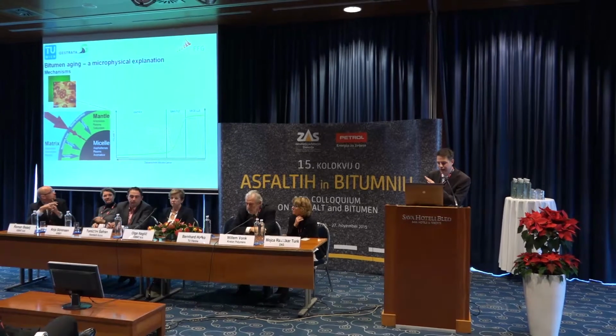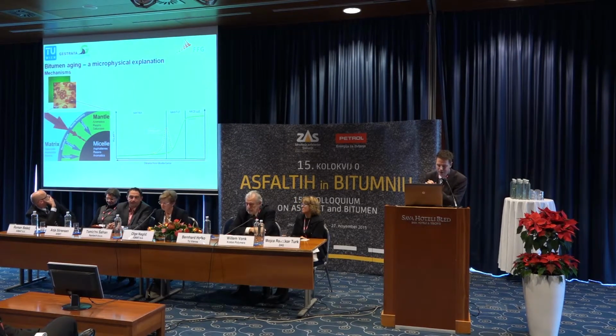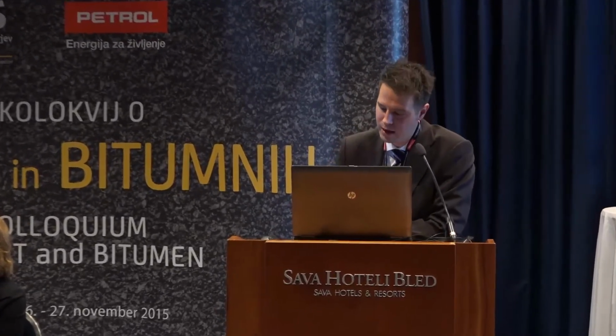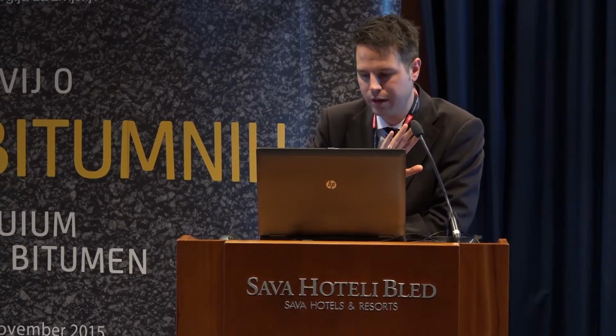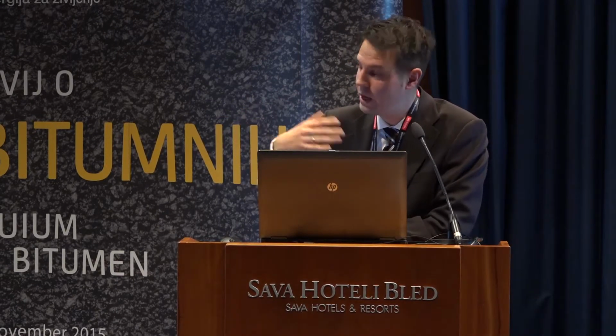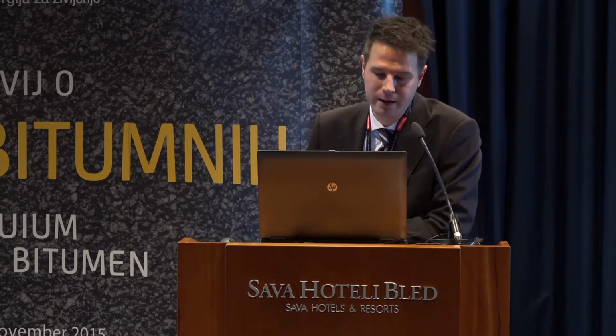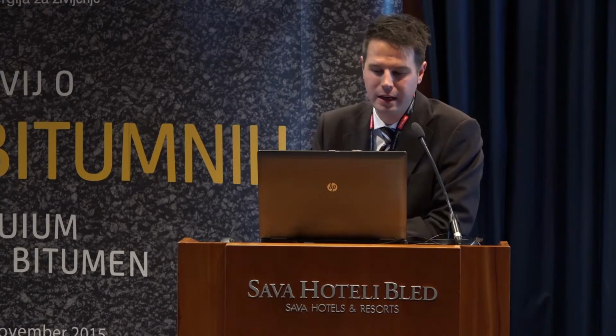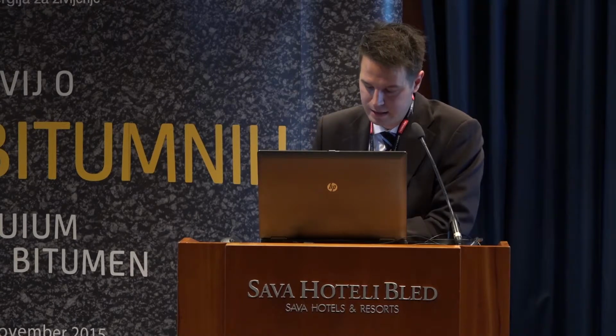This also means that we have now a very steep gradient of our polarity line, which means we get something like a temporary embrittlement. This would mean we would get a quite brittle bitumen at a very early stage. But the good thing about bitumen, and about any material, is that at higher temperatures the complete system gets more mobile, so all the phases get a higher mobility, and we get temperatures up to 55, 60 degrees in summertime in bitumen. This means all the phases get more mobile, and we can transport the high polar things towards the micelle center. So what we again get is a very nice, quite smooth line in our polarity, which means the dispersion works again, and temporary embrittlement is removed, and we still get a very smooth, nice bitumen as we know it.